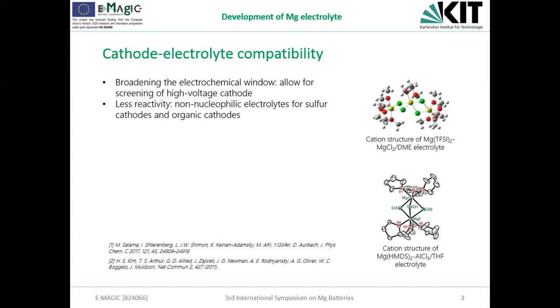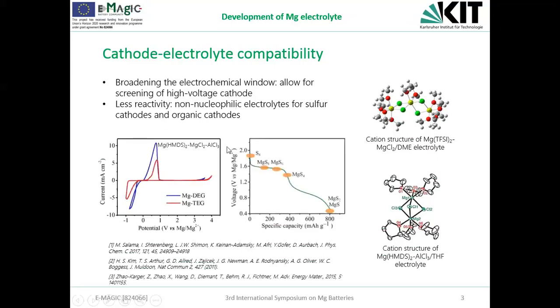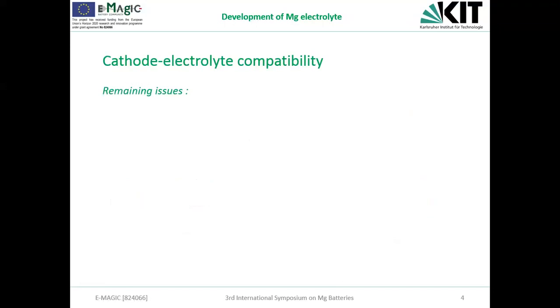For example, the magnesium TFSI with the magnesium chloride case, as highlighted by Professor Aurbach, and also the magnesium HMDS electrolyte. This is also in combination with the aluminium chloride. So in this case, we could see from the CV that we have an extended oxidation stability of up to 3.5 volts, which is much improved compared to the APC case. And also, as demonstrated in the magnesium sulfur cell, it's compatible with the electrophilic cathode materials. So, in fact, with this non-nucleophilic electrolyte, we could already investigate the magnesium storage capability in a broad range of cathode materials, but then there's still the remaining issue, the chlorine.